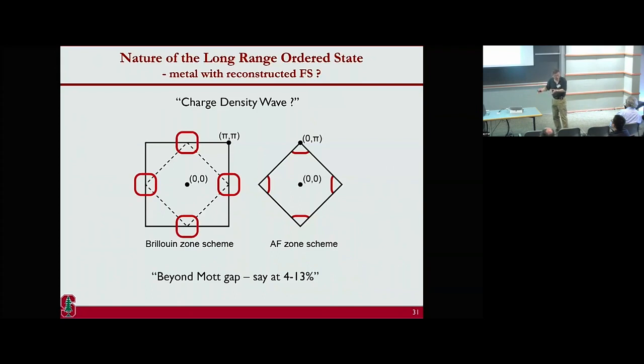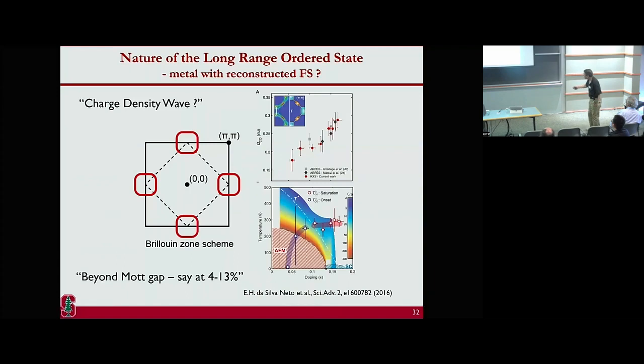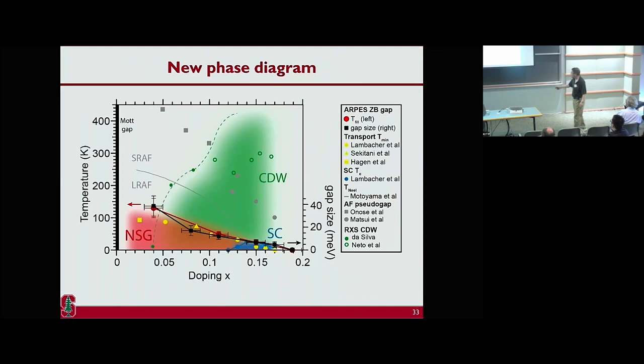One of them will be charge density wave. And indeed, as reported by, I think, the UBC group, they see the vector here is exactly this vector somewhere here for this kind of doping. Okay, so it could be a charge density wave gap. Except we measure this gap as a function of doping. You see it monotonically going down like this, but when you look at charge density wave, it behaves like that. Both the temperature dependence, doping dependence, and the temperature scale are very different.